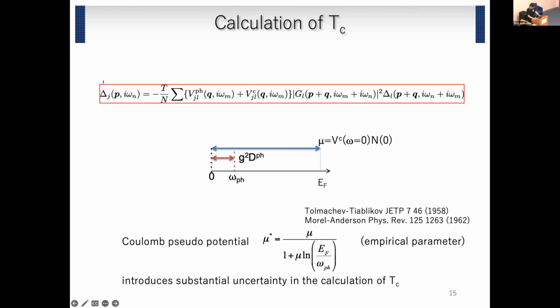problem when we solve this gap equation is that the energy scales of these two interactions are very different. Namely, the attractive interaction is finite only for states in the vicinity of the Fermi level, but the screened Coulomb interaction works for states in a wider energy scale, as large as the Fermi bandwidth. And this mu is the screened Coulomb interaction, and we try to solve this equation at low temperature to cover the energy scales of the bandwidth. We have to introduce many Matsubara frequencies. So that is the problem.